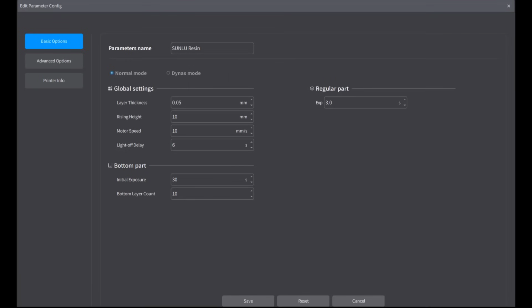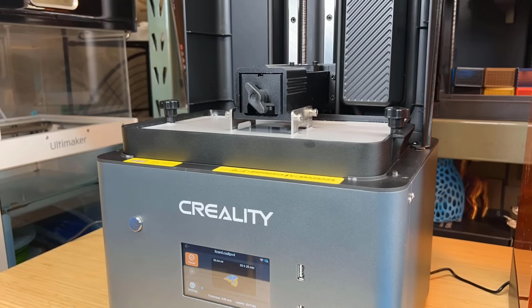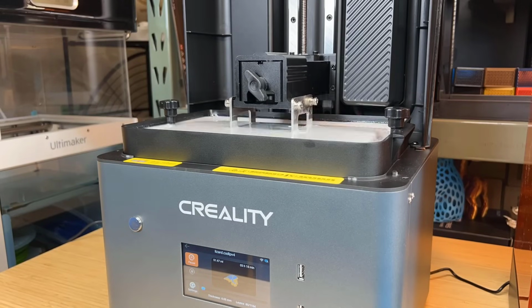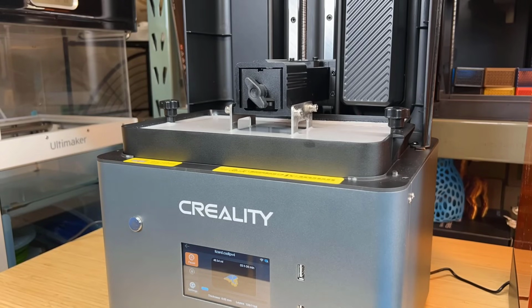For the printing parameters, I will use a 0.05 mm layer height with a 3-second exposure time for normal layers and 30 seconds for the bottom 10 layers. The platform will rise by 10 millimeters between layers at a speed of 10 millimeters per second, and the light off delay will be set to 6 seconds. While these settings aren't the fastest and don't push the machine to its limits, they should work well with most resins.